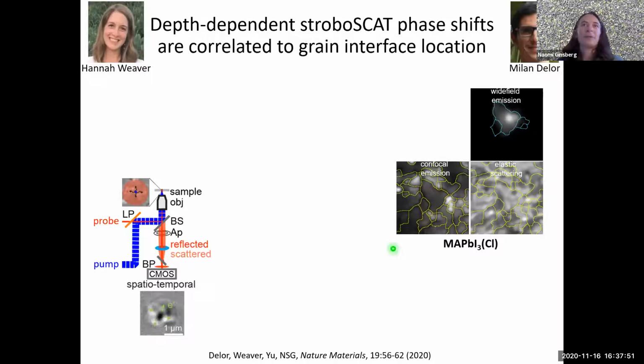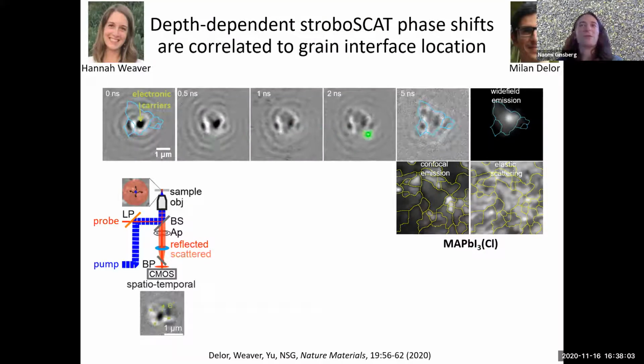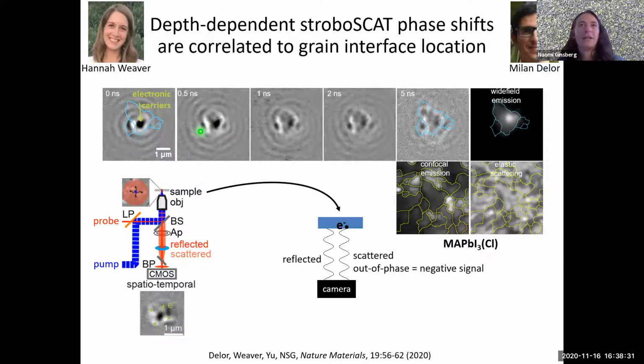So first of all, Hannah used in situ ground state images like these to identify interfaces between domains in this halide perovskite material. And in this series of stroboscat images, you can see that the photo-generated charges initially appear as dark or negative contrast relative to the background. We notice that these lighter regions that show up, the positive contrast, correlate with locations of interfaces. So remember, this is an interferometric scattering approach, and if this is an interferometer, we should have access to depth information. And so what we hypothesized is that the phase of scattering is changing due to scatterers traveling deeper into the film at the location of these interfaces. Okay, so you can start to see where our hypothesis came from.